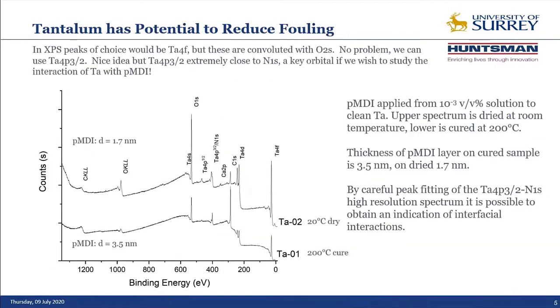So why are we worrying about tantalum? Now, that's a key point for this particular work. As I said, when we started working with Huntsman with their research centre in Everberg in Belgium, what we were doing was looking at the nature of the interactions that gave rise to adhesion. More recently, over the last 4 or 5 years, we've been working with the manufacturing plant in Rotterdam and worrying to a certain extent not about adhesion as a good thing, but adhesion as a bad thing. So the fouling in the chemical plant that is used to make this methylene diphenyl diisocyanate.